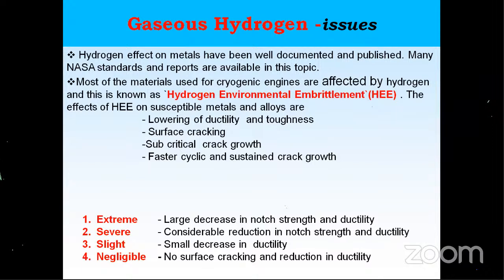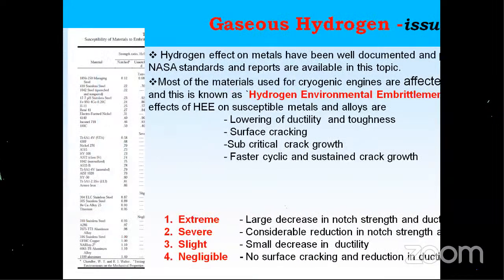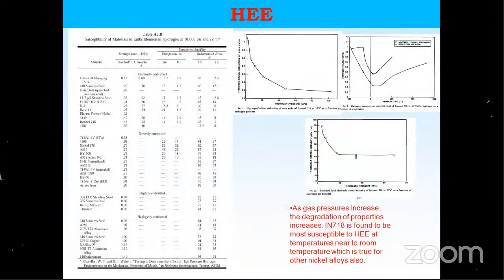Why am I telling all this? Forget about the rocket engine and rocket fuel. When you use hydrogen as an automotive fuel, this is going to be very important, especially in hydrogen gas handling: your valves, lines and tanks. There is no issue with tanks because aluminum tanks are available ready-made. But for the hydrogen lines, you have to choose very good material, especially for the valves. Valve material is going to be important. So we have categorized them: extreme, severe, slight and negligibly brittle materials. You can see that, right? The worst material is maraging steel, and almost all maraging steels are bad.